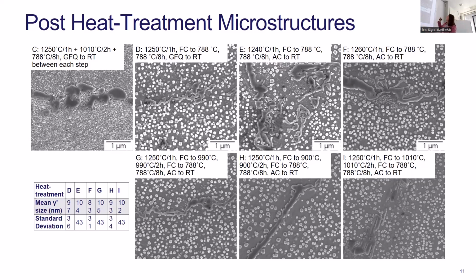If you look at probably this third one here and the fourth one there, you can see around the grain boundary, we have the tertiary gamma prime coming out. So the only two heat treatment conditions that we didn't have that were the ones that we had the second heat treatment stage subsolvus to the gamma prime.